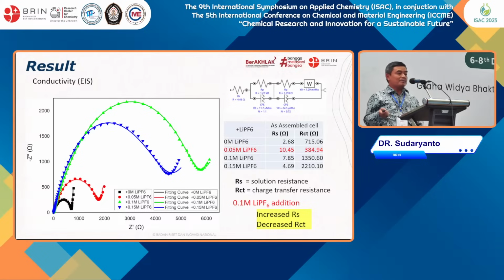If we check the impedance, we can see that adding LiPF6 to the blend of LiTFSI and LiBOB changes the impedance property. Interestingly, a small addition of LiPF6 increases the solution resistance, meaning it decreases the conductivity, but it decreases the interfacial transfer resistance. So RS can be considered the internal resistance, while RCT is the resistance at the interfacial part.